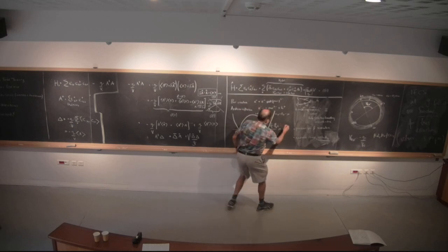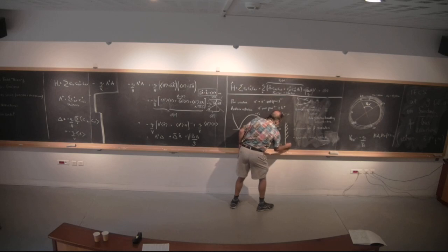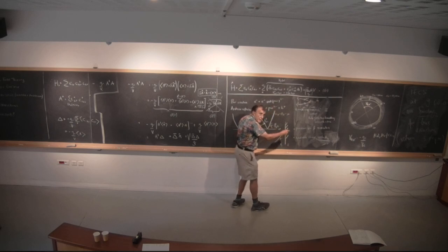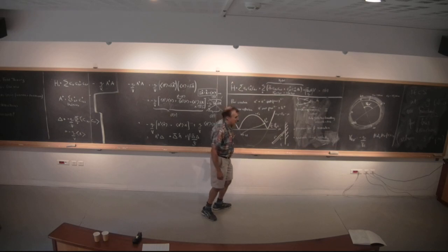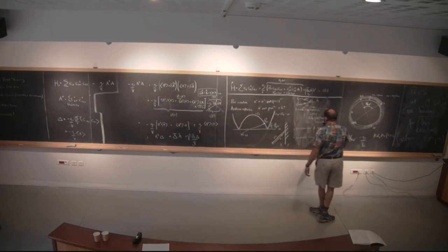So it turns out that you can actually do this at a superconducting normal interface. You can send in an electron like this. Here comes the electron. It forms the zero momentum condensate, and the hole comes right back like that. It bounces back like that, okay? And you can actually observe that experimentally. It's called Andreev reflection, and it's really weird because it time reverses everything. So it reverses charge and it reverses velocity.